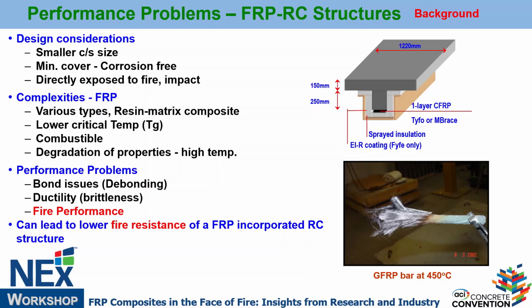Then, you don't have to provide too much cover, right? As pointed out, all our fire resistance is based on how much cover you provide based on the current codes. You don't need that cover. You know why? Because it's non-corrosive. For steel, because of corrosion we put in cover, and that supplements the fire protection as well. Then it's directly exposed to fire. Before, your reinforcement was protected, right? FRP reinforcement is secondary reinforcement.